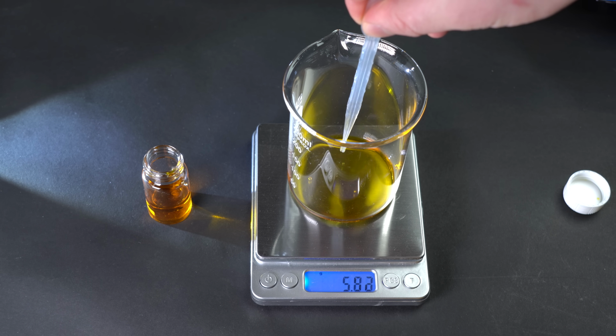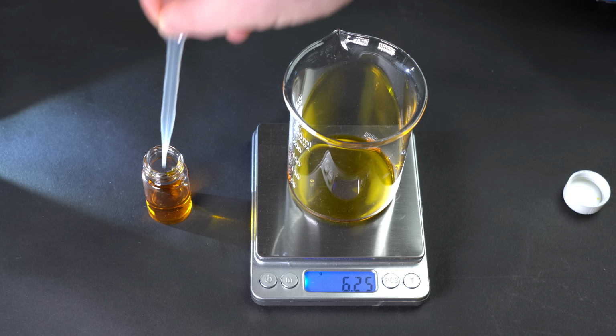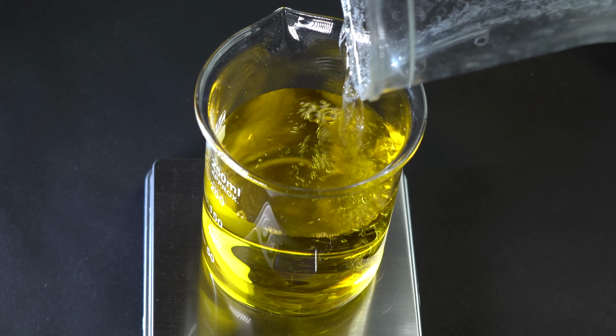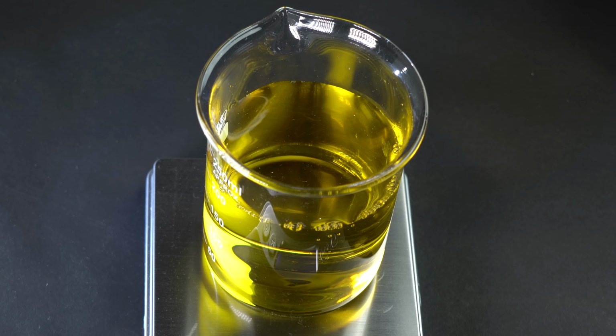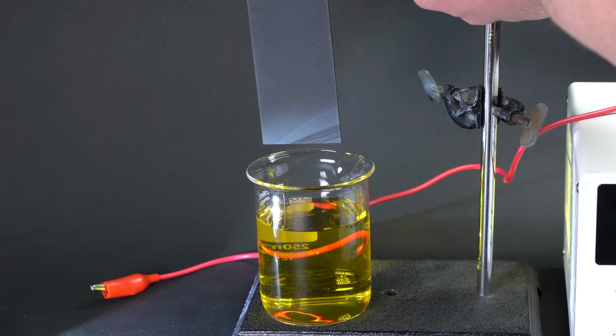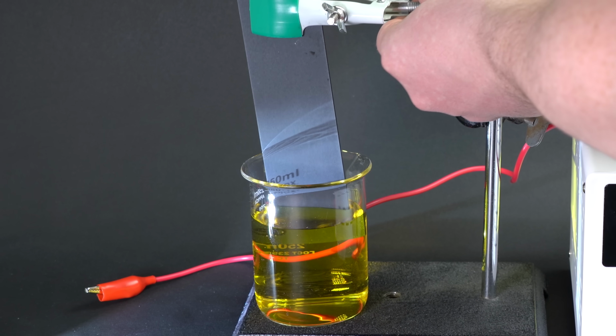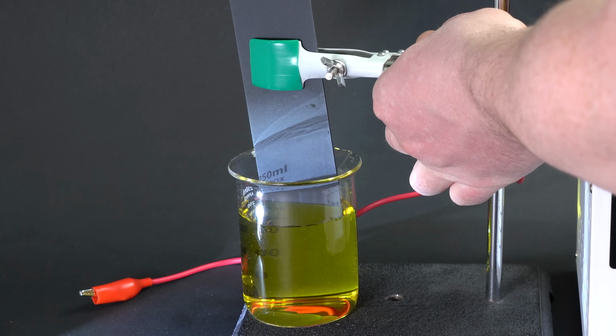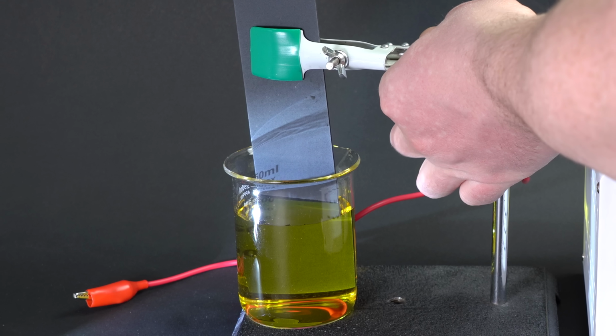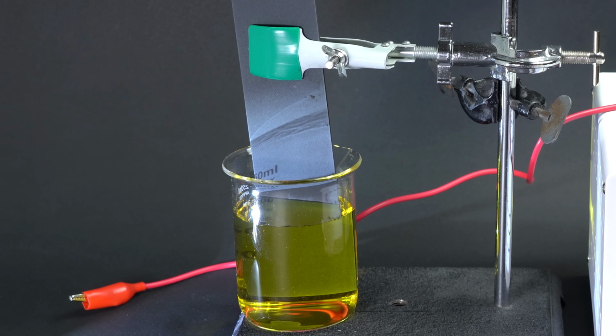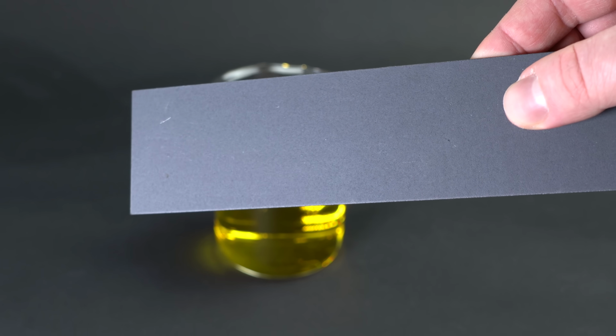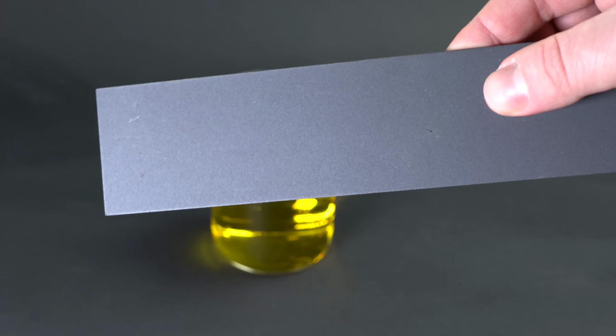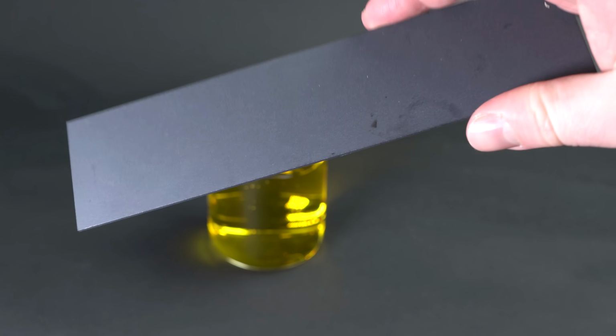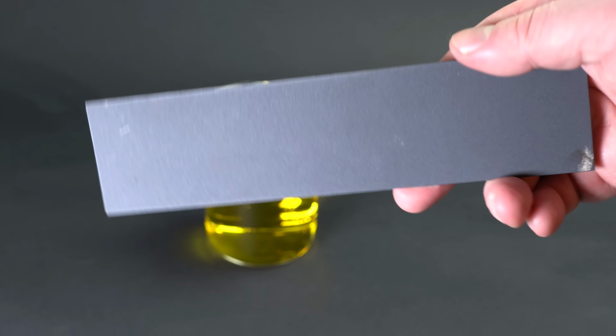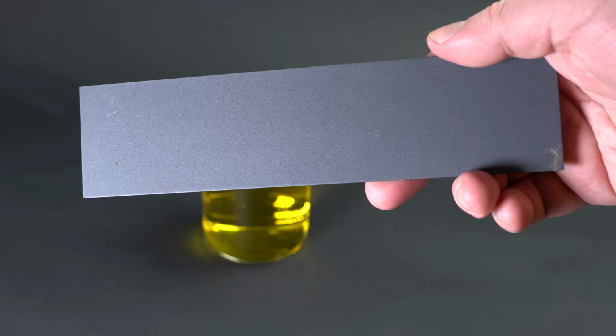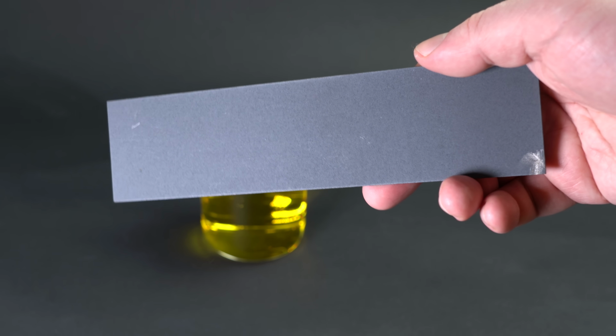And after that, I'm pouring 9 grams of this solution into another beaker, increasing the volume of the solution to 200 milliliters. Now I'm lowering a pretty expensive and durable titanium electrode covered in iridium and ruthenium oxides into the obtained light yellowish solution. Such electrodes are used in gold and rhodium plating in order for the reaction to run more smoothly and for the solution not to get tainted in such an aggressive medium by the disintegrating anode.